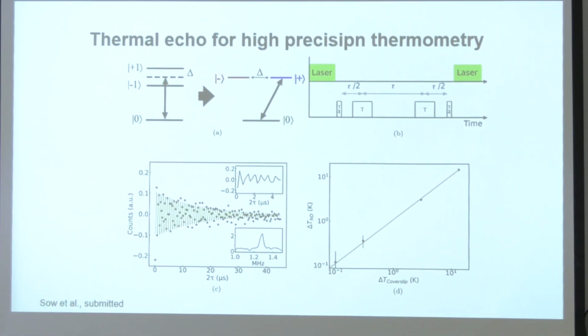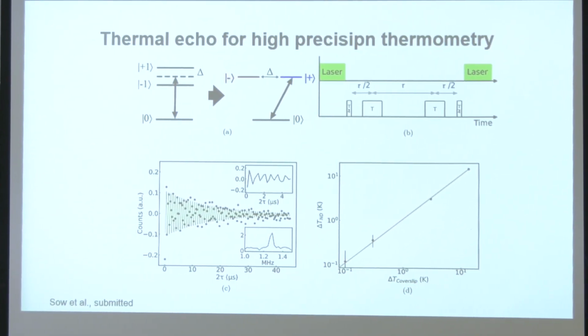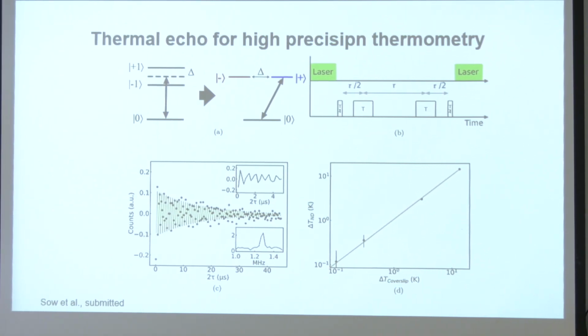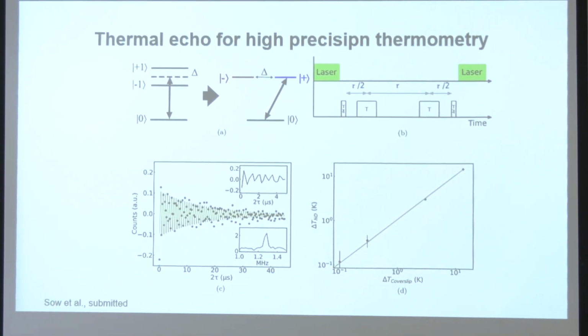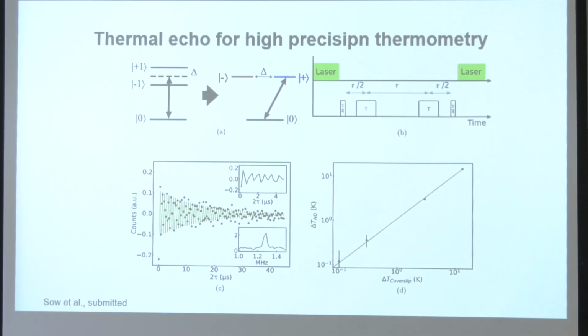Maybe also one point about precision. So many experiments have been done by a very simple technique, just scanning the frequency and tracking the transition of NV center, but you can also do better using a more advanced coherent control technique. I show you here some spin echo that is tuned so that it is sensitive only to frequency span between -1 and +1 states and 0, and not sensitive to magnetic field fluctuations, creating shift of -1 and +1 kind of in a synchronized level.